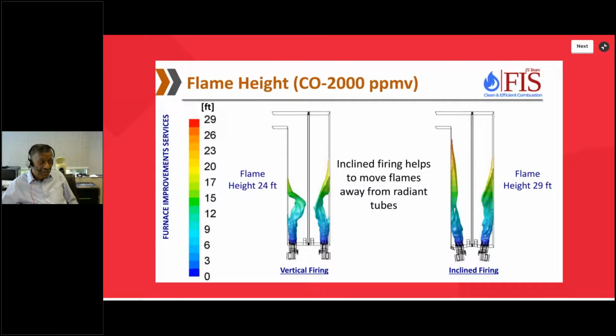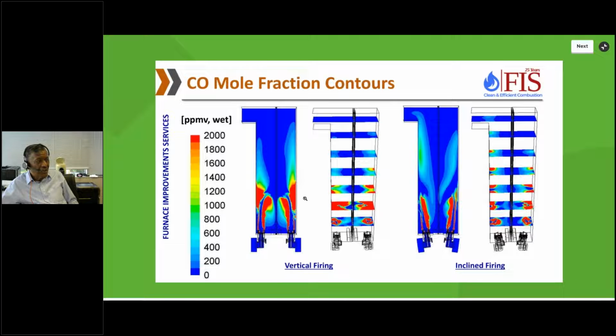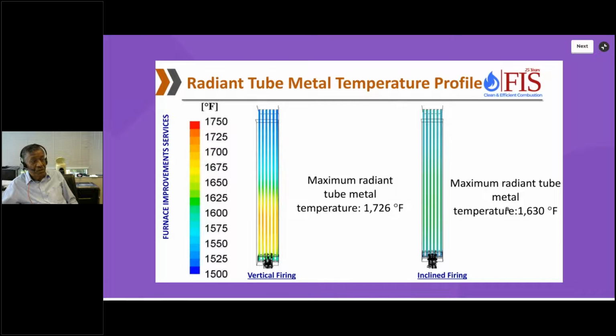It can be done using your existing burners; you don't even have to change the burners. This is again showing the mole fractions over here. A CO mole fraction of 2000 ppm is considered a flame. And you can see over here, the flames are almost touching the tube, high temperature. Whereas when we put the inclined firing, we are able to get flames more towards the wall, and this is all clear. And you can see almost a 90-degree reduction in the tube metal temperature. So I think it has a place. If you are having any issues with high tube metal temperatures, you can talk to us and we will be able to see whether your furnace is a good candidate for inclined firing, whether it can really reduce the tube metal temperatures. All right, that's all I had.